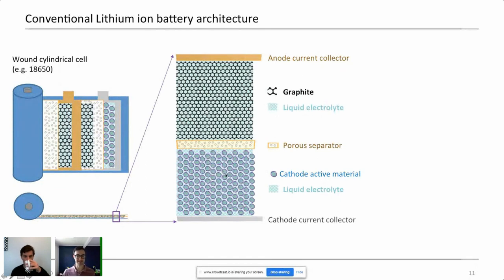This next layer down is the cathode, which again includes particles that are an active material of a cathode that is again a host that lithium ion will sit in. It's something that has a very high affinity for lithium. So there's a strong driving force for lithium to sit in this cathode material. And the difference in the lithium affinity between graphite and the cathode active material is what provides the voltage in the battery. And between these particles are again a liquid electrolyte that's responsible for delivering the lithium ions.